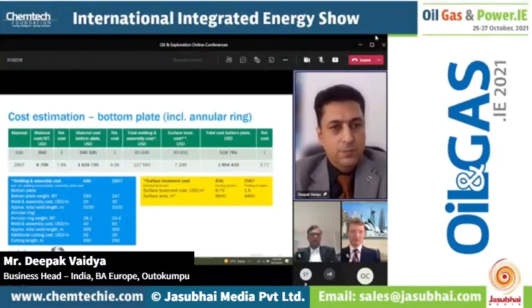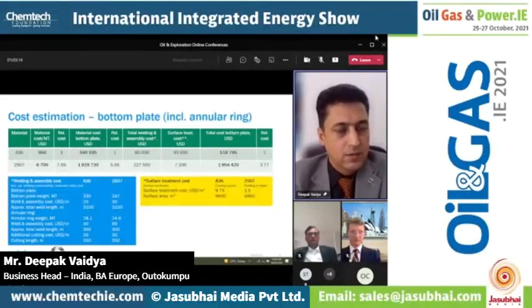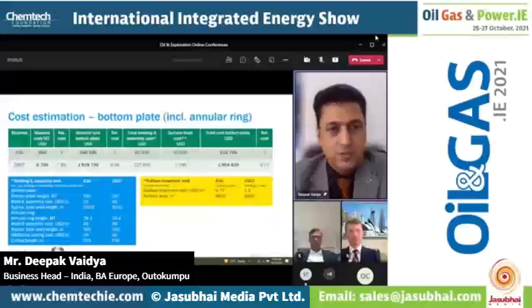The material cost, if you compare, we know the weights. For A36, it was around 358.1 metric ton, whereas for super duplex, it was 273.6. We multiplied it with the cost of raw material. That worked out to be $340,195 for A36, and for 2507, it is $1,819,720, which means that the relative cost, which was earlier 7.05 times for super duplex, reduced to 5.35 times by utilizing the strength of super duplex to reduce the thickness.